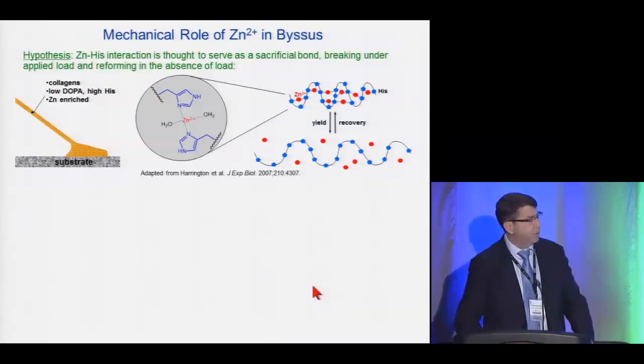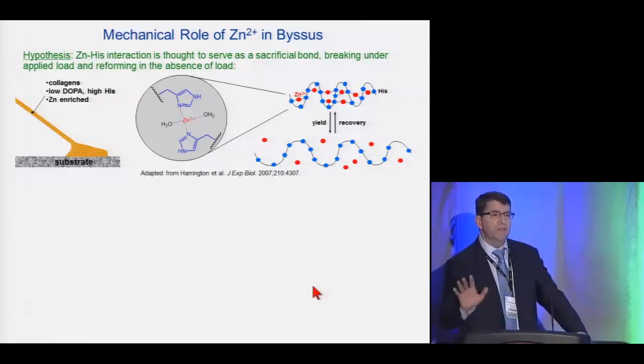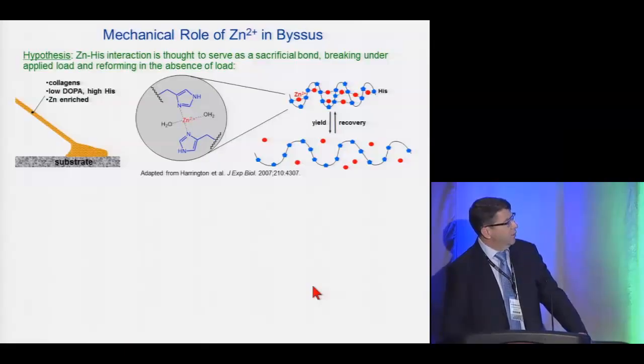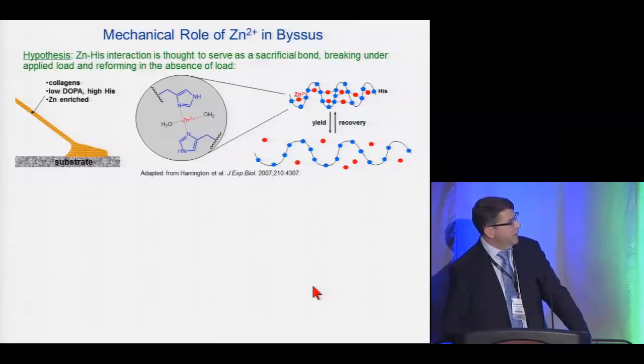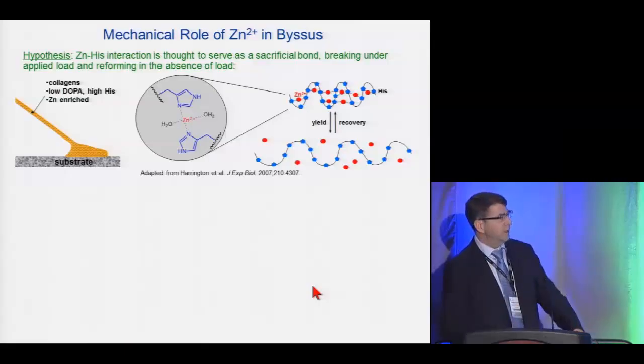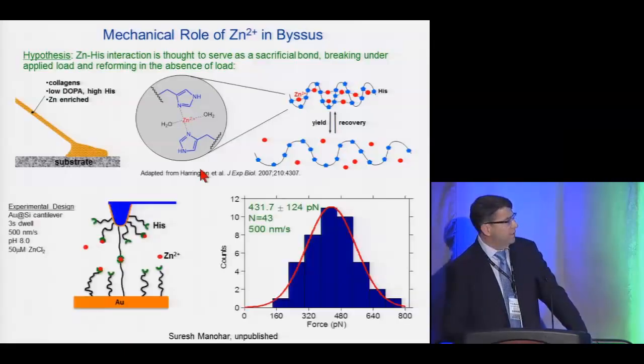Then more recently, we've looked at the role of zinc as well, and this involves a different residue, histidine residues in the core collagen. So the threads are made of modified collagens. Very interesting proteins as well. They have N-terminal and C-terminal regions which are incredibly enriched in histidine. Almost every other amino acid in those regions is histidine. And they're also enriched in zinc. And so this hypothesis of zinc also forming a sacrificial mechanical bond has been around for a while as well. And this is something that we're currently looking into, again, with single molecule force spectroscopy by probing the force of rupture of this bond between 2 histidine residues bridged by a zinc.